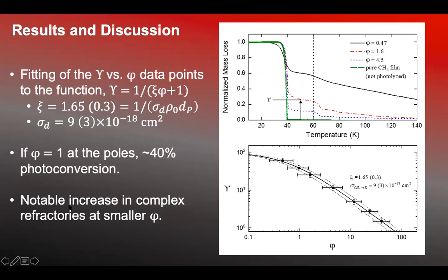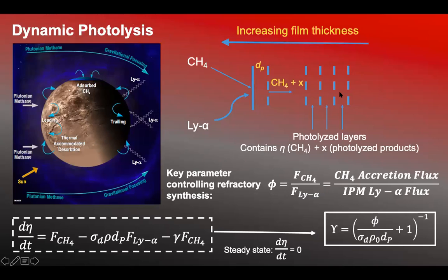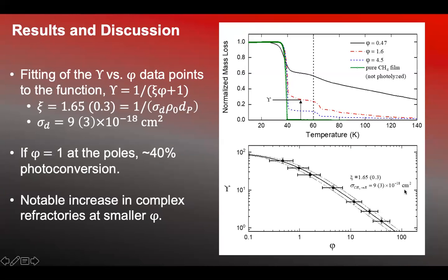Another key point going forward, expanding on these results, is that there's a notable increase in these complex refractories at smaller phi values. In other words, where that incoming methane flux is much smaller than the Lyman alpha flux. So there's a much greater photolysis happening than the pace of actual methane deposition. And you can see this here with this very long curve of all this stuff that's taking a long time to melt away. There are way more complex refractories. And again, a lot more investigation will be needed to determine what exactly those refractories are and what role they have in the overall reflectance.